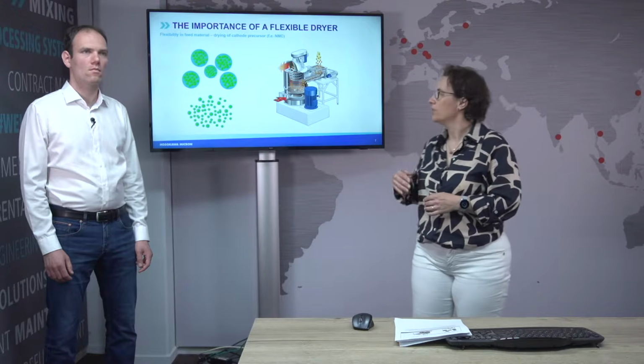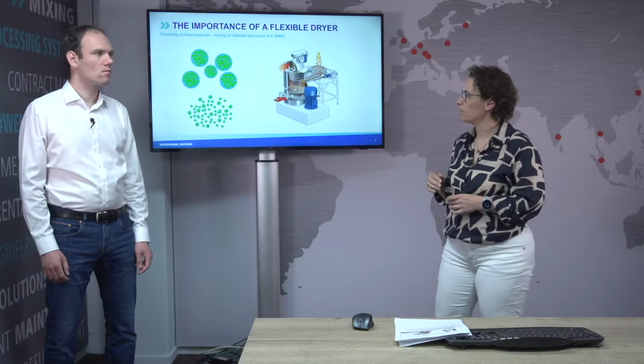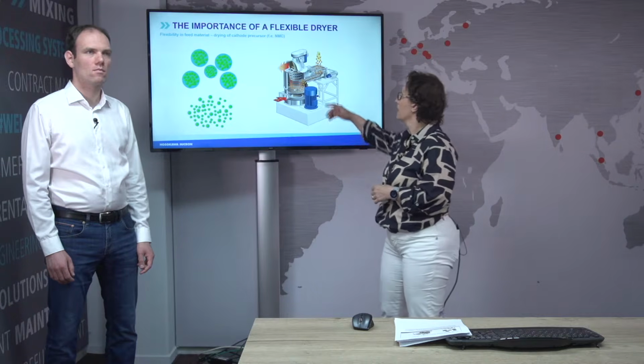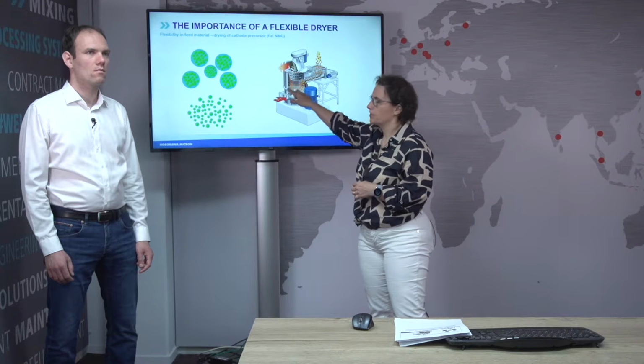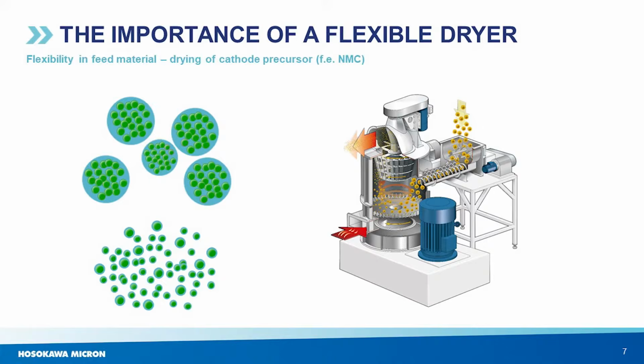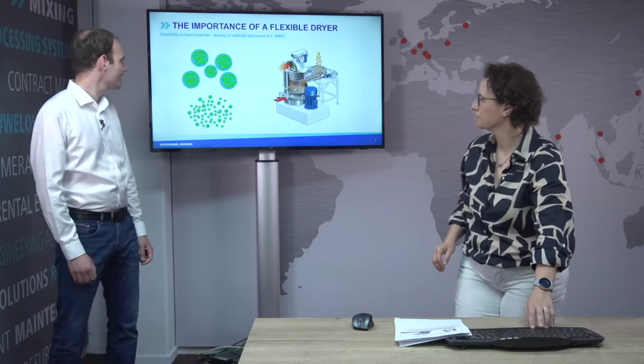So drying is one of the first processes where Hosokawa gets involved in the battery industry. For continuous drying of, for example, precursor material, we use our flash dryer. The product, a filter cake or a slurry, will fall into the drying chamber where we have a dispersion disc. The dispersion disc makes sure that the larger agglomerates in the feed material break into smaller particles, creating a high surface area which is sufficient for drying. We dry to about 1% end moisture.